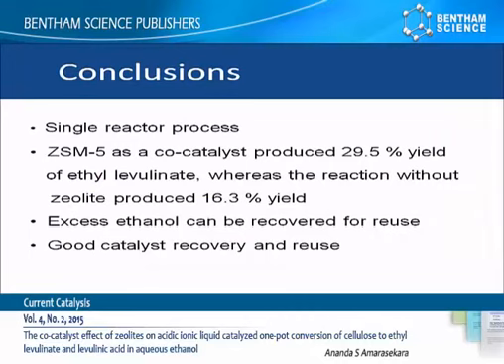Whereas the sample without any zeolite co-catalyst produced only about 16% yield under similar conditions. In addition, excess ethanol and catalyst could be recovered as well.